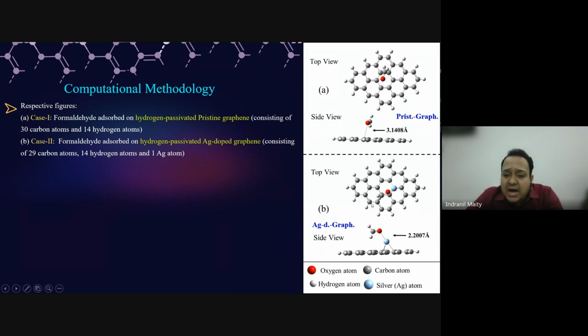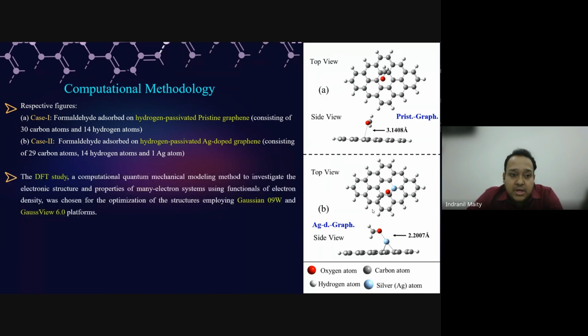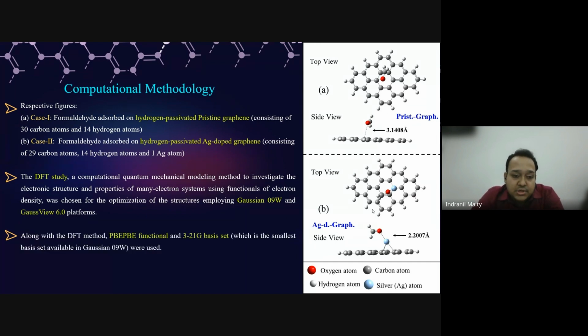And after optimization, these two structures have been developed, and the structure basically has carbon atoms, hydrogen atoms, and in the case of the silver doped graphene sheet, the silver atom. As I already mentioned the names of the software, along with that, the simulation was carried out with the PBE functional, along with the basis set of 3-21G. And the adsorption energy, which is crucial for the sensing application, to find out how much adsorption probability there is, was evaluated with the help of this formula.